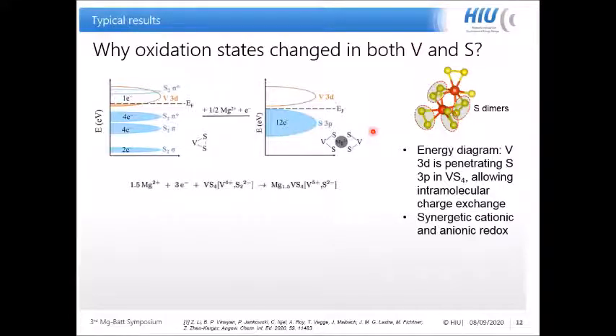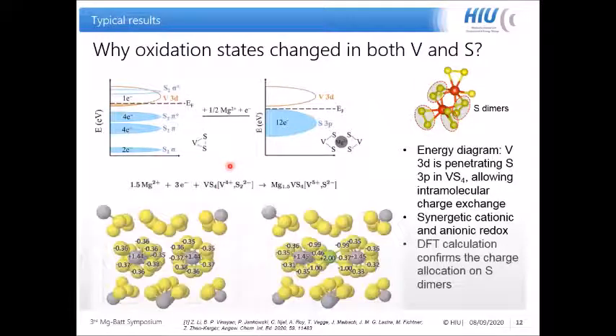And with the synergetic cationic and anionic redox, we could theoretically achieve 1.5 magnesium per VS4 structure. This mechanism is also confirmed by a DFT calculation, where we have seen the charge allocation is mostly on the sulfur dimers.